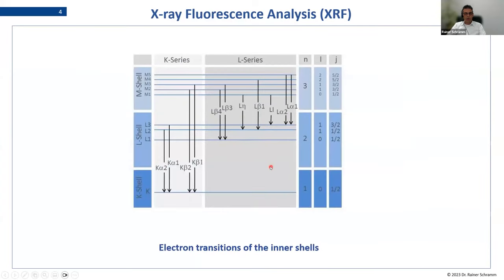A different way to show it would be that we have here our inner shell, K, called the K shell. Then we have the L shells and the M shells. If, for example, in the K shell a gap is produced, and an electron from the L shell is filling it, we call the lines we see K alpha. If it's coming from the M shell, it would be K beta. And also in the L shell, gaps will be filled from the M shell, and then we get an L line pattern.